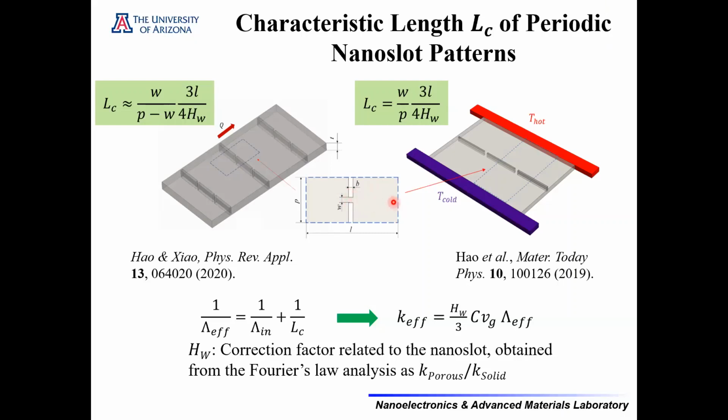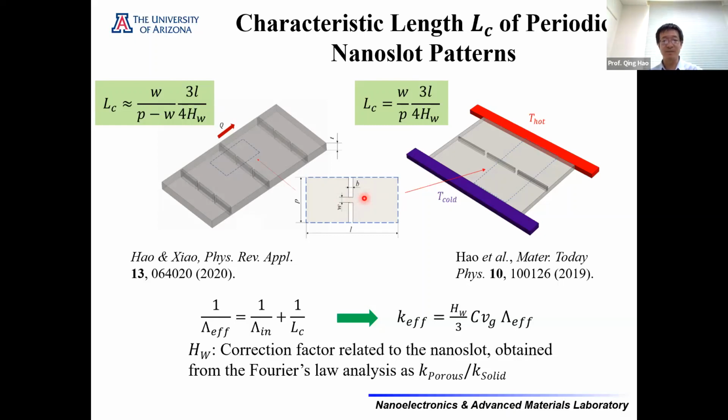Yeah, but it would depend on what kind of thermal conductivity you're probing, whether it's effective thermal conductivity or whether the ballistic resistance is actually taken into account. Yeah, ballistic resistance doesn't depend on the B value, because the ballistic resistance arises when phonons come out of this geometry constriction region into the left and right space. So if you increase the B value, ballistic resistance is not affected. Ballistic resistance only depends on the W value. Of course, this is a very important aspect for nanofabrication. If B is very small, that's the ideal case and your whole analysis is very simple. If B is large, you have to consider those nanowire regions.